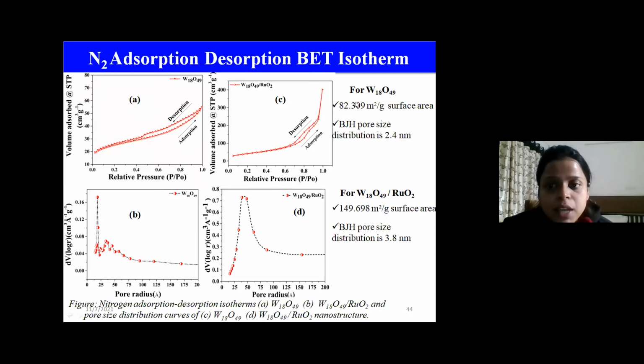This is the BET isotherm, and the W18O49 is giving 82.309 meters square per gram of surface area with a pore size distribution of 2.4 nanometers, whereas the hybrid material is giving a huge, almost double enhancement, 149.698 meters square per gram. So this shows that after incorporating the ruthenium oxide nanomaterial in W18O49, there's a huge enhancement in the surface area, which can help the electrode material interact well with the electrolyte.